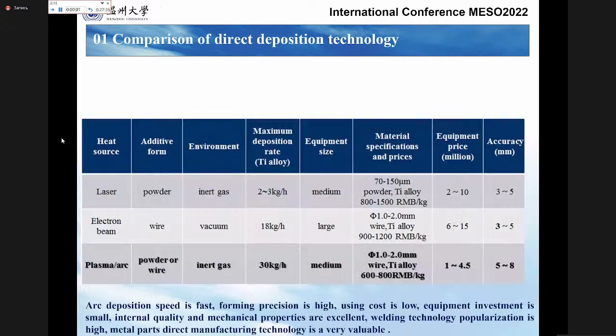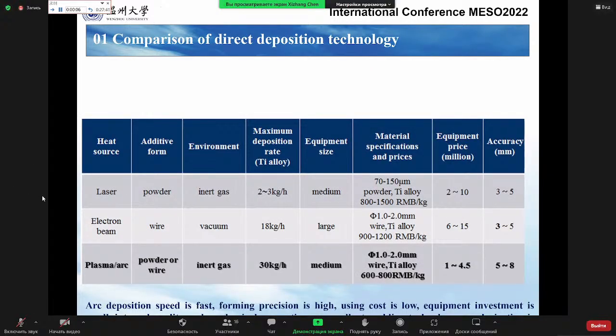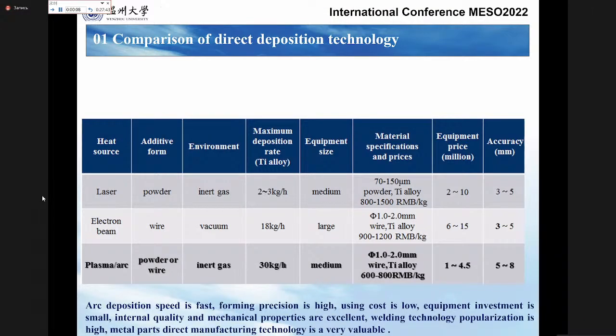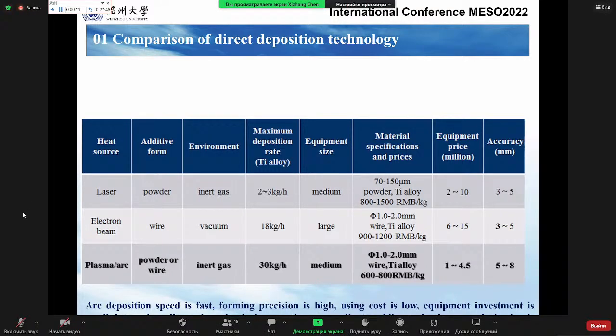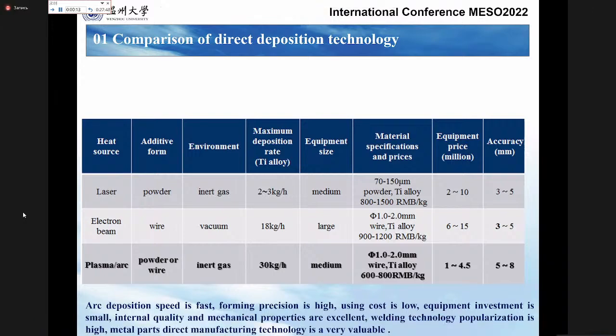Electron beam. That means the materials are fed directly, not like SLM. Of course, I did some SLM research, but it's not the focus today. We can compare the direct deposition technology. You can see laser, electron beam, and arc. For the efficiency, I think arc is the highest. It can be up to 30 kilograms per hour. It's about 10 times that of SLM.